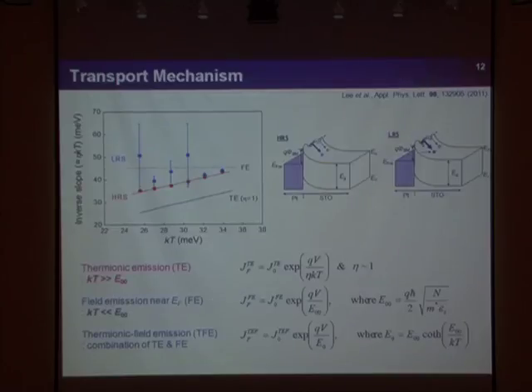We also examined the transport mechanism. In the HRS case, this is the inverse slope of the IV and temperature curve. If the transport is dominated by thermal emission, this curve should be linear according to the simple equation. However, if tunneling is important, the IV characteristic will look like this.